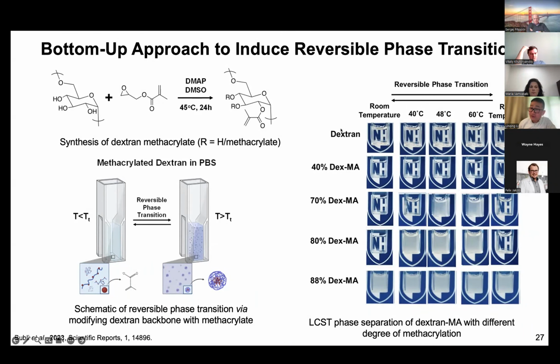As you can see, native dextran is hydrophilic, so even when you increase the temperature, it doesn't show any phase separation. Even at low modification, 40%, you don't see any phase separation. At 70%, you have to increase the temperature to 48 degrees, then you can see the phase separation, and when you cool down to room temperature it becomes clear again. This is of course dependent on your modification. At 88%, you can create a phase separation at room temperature, which allows us to handle cross-linking hydrogels and the gelation formation. Of course, when you cool down further to 10 degrees, the solution becomes clear again.